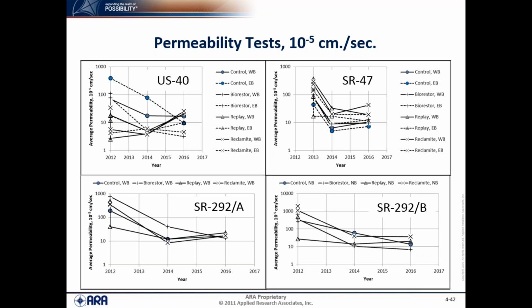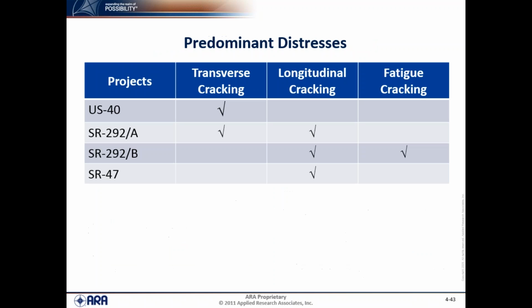You can see that the field permeability tests were done on an every other year basis, not on an every year basis. So you can see from the initial results, they go down each one, and then between 2014 and 16, they were relatively about the same value on the average. The average values were relatively about the same. But there's a lot of variability in field permeability.